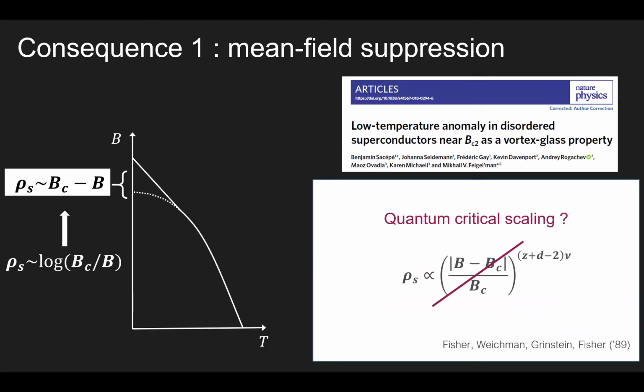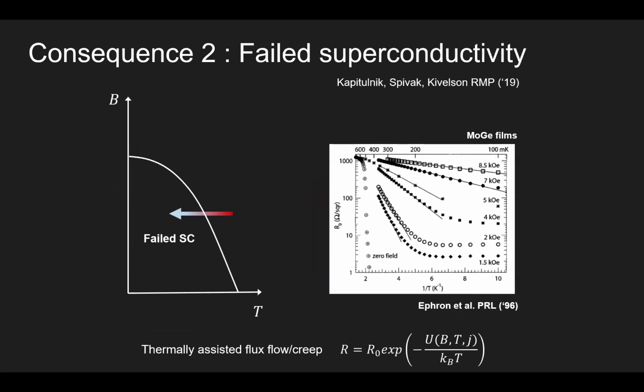Also, one of the important consequences is that this mean field scaling is not compatible with quantum critical scaling that has been extensively used in this field to extract critical exponents. I'm not claiming any generalization of this story. This is perhaps specific to this material, but I think all the inconsistency in this kind of analysis perhaps calls for revisiting this transition as a function of magnetic field in this indium oxide.